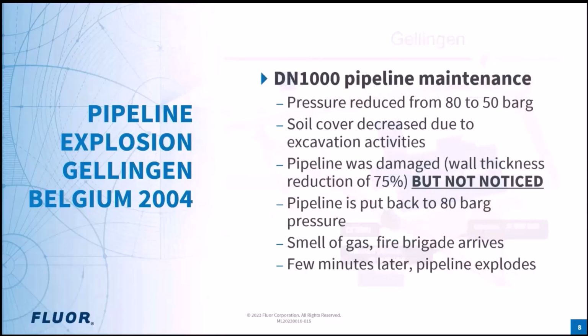So what happened that day? The DN1000 pipeline was in maintenance. Therefore, the pressure was reduced from 80 to 50 bar. At site, there were excavation activities going on for site finishing. Therefore, the soil cover on top of the pipe was decreased. During these excavations, the pipeline got damaged, but not noticed. Investigation afterwards demonstrated a wall thickness reduction of about 75%.